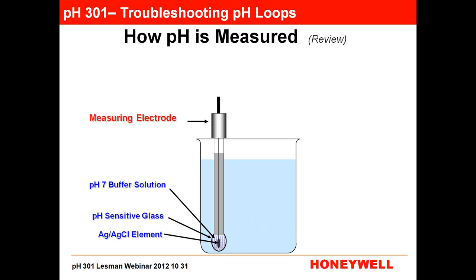It's 0 millivolts. At 6 pH, you're going to have 59.165 millivolts, or 59 millivolts approximately. At 5 pH, 118 millivolts. If you go above 7, at 8 pH, you get 59 negative millivolts. At 9 pH, you're up to minus 118, et cetera. So you have this measuring electrode that varies voltage depending on the solution value.